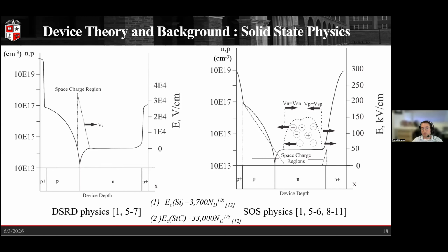So a typical interruption time for a DSRD is going to be single nanoseconds, maybe up to 10 to 20 nanoseconds on the very long side. By contrast, with the SOS device, you can typically see interruption times from 10 to 20, 30 nanoseconds. And so that's one of the biggest distinguishing factors between them, is where the actual space charge region is formed and how fast that interruption actually occurs. So the DSRD is going to be faster, but with that comes the caveat of typically lower energy.